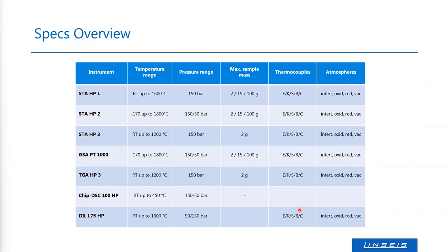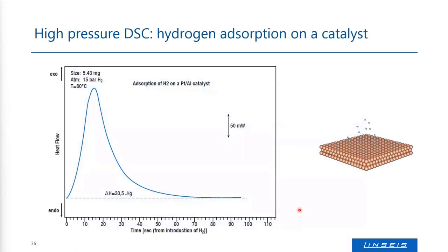There is a broad range of high-pressure applications, including adsorption. Here you can see an example of our high-pressure DSC, used to measure the sorption heat — specifically the sorption of hydrogen on a platinum-aluminum catalyst at a constant temperature of 80 degrees Celsius. Hydrogen was applied at 15 bar, and during the sorption, which is an exothermic process, the corresponding enthalpy was evolved.